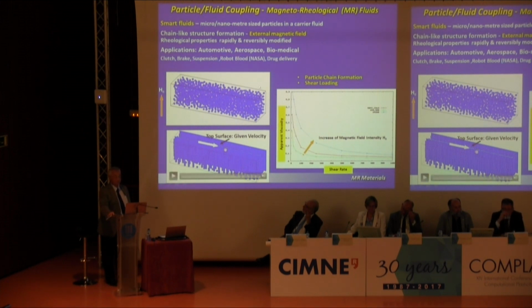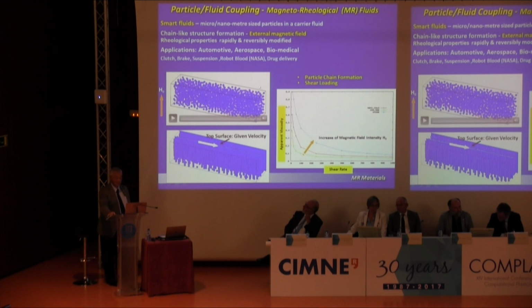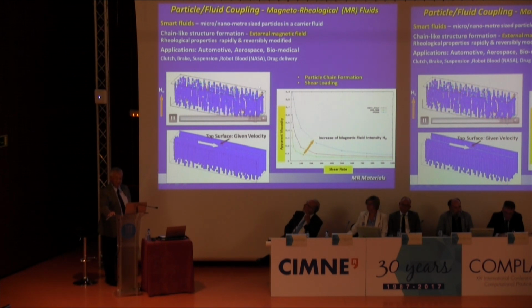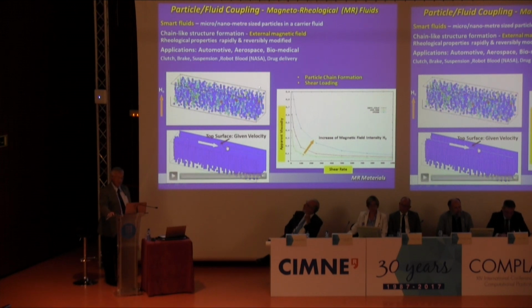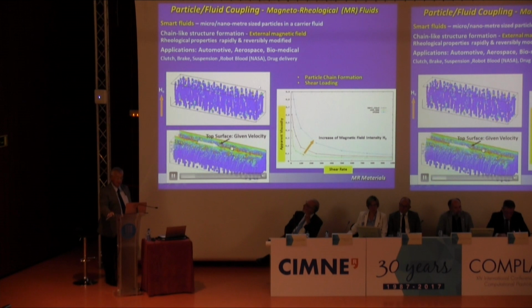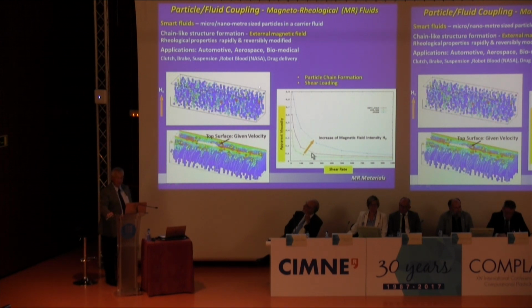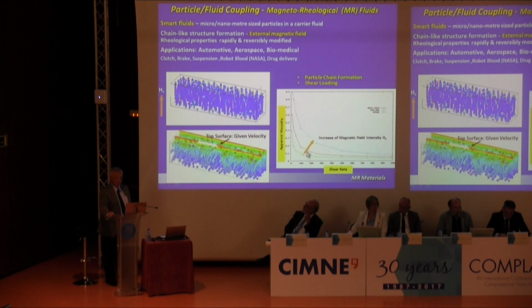I'll show you one more example, which I shouldn't show, because it's got nothing to do with plasticity, because the clue is here, it's all reversible. But essentially, the methodology is exactly the same: we have particles in a carrier fluid, you apply a magnetic field to it, and this magnetic field will actually line up these particles in chains. And then this actually affects the viscosity behavior. So we can measure that by giving the top surface here a given velocity. And then you can calculate the reactive force, and from the reactive force, you can compute the viscosity. And what you find is that you've got a variation between the shear rate and viscosity, which changes depending on the magnetic field intensity that you apply.